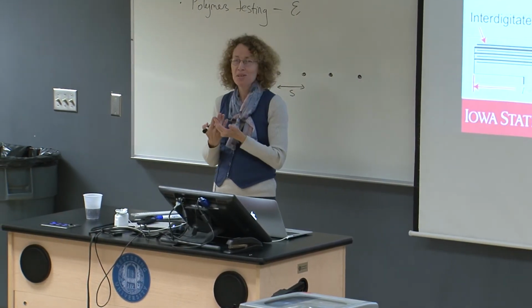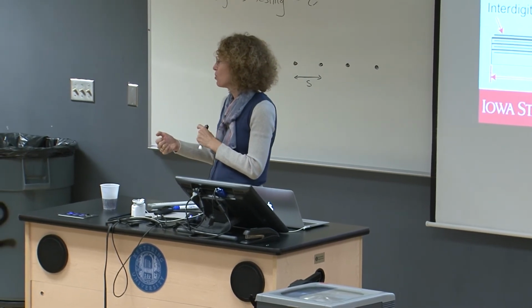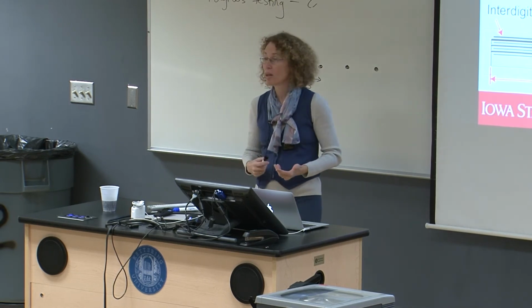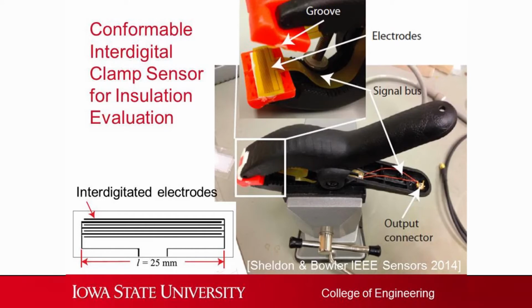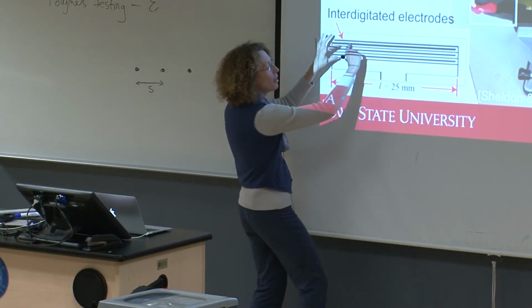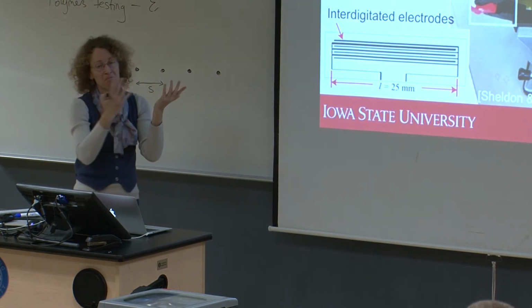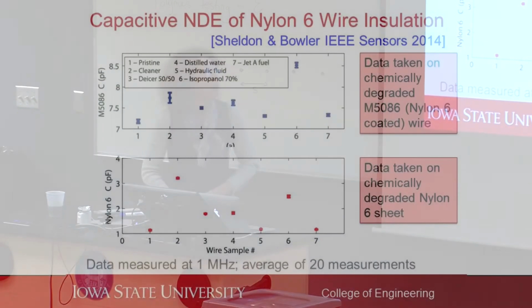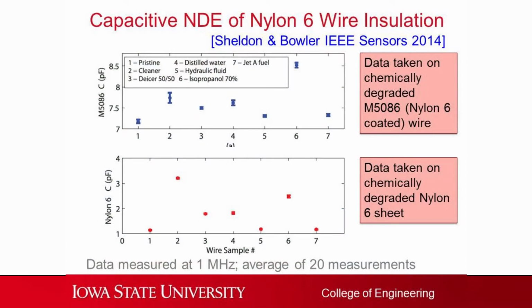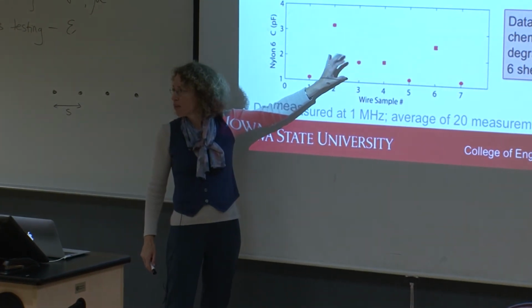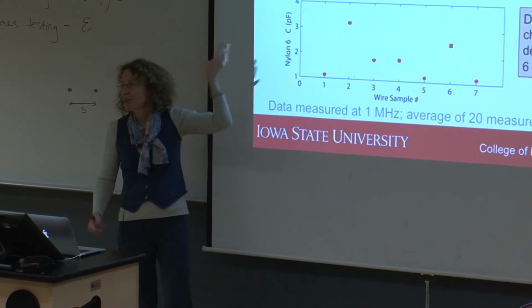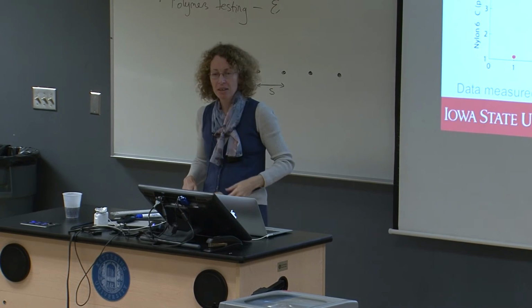So that result gave us some hope that if we developed a sensor to clamp onto a wire, we might be able to tell if it was degraded in some way by a chemical. And so this clamp was developed. The electrode area actually looks like this. So interdigital electrodes in this kind of way that you would lie the wire along here, and you clamp down on it, you take some measurements. And this is the result that we got for those different fluids here. On a typical aircraft wire with a nylon coating, we see that we can get some distinction between those different ways it was degraded. And down here, we compare that with what we got on the nylon sheets. We don't expect them to track perfectly for various reasons, but they do correlate pretty well.